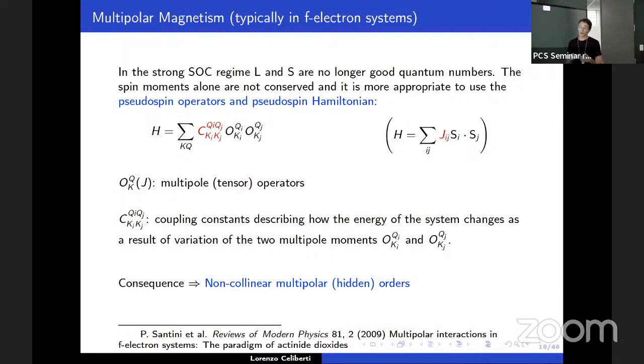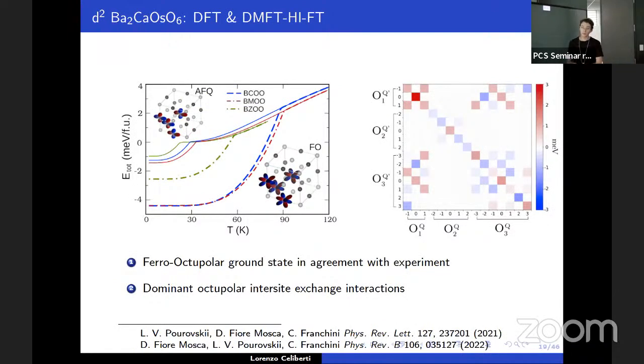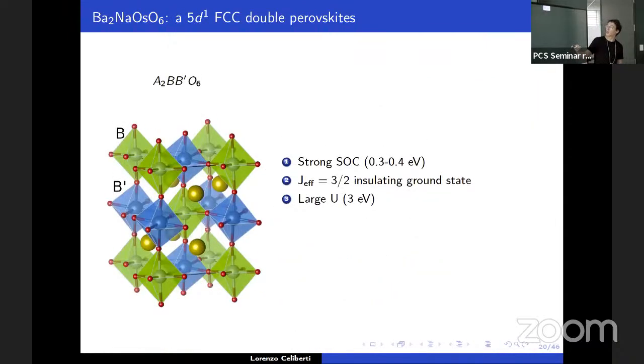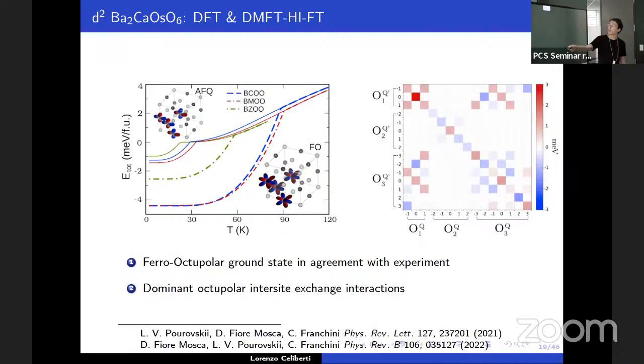And another consequence of the presence of these operators is that you can have the so-called hidden orders, where you have an ordered phase where you don't have magnetic moments ordered, but another order parameter, which are these multipole operators. An example of this is barium calcium osmate, which shows a ferro-octupolar order, meaning that you have octupole ordering, so tensor operator of rank 3. And here you can see the interaction constants between these multipole operators calculated within the dynamical mean field theory, and you can see that there is a dominant interaction in this region here, which is the octupole interaction.